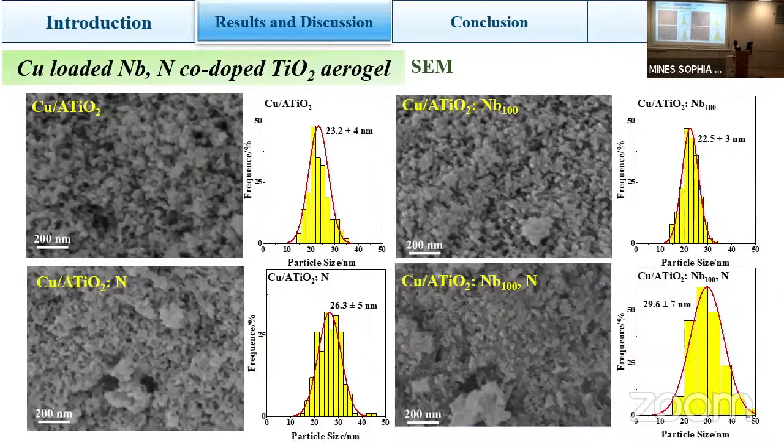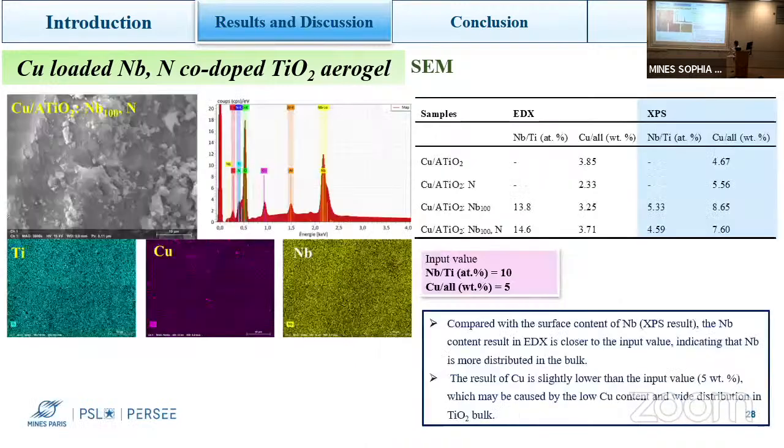And then we're using SEM to characterize its morphology. You can see that even loaded with copper, with metal, and calcined in ammonium, our catalyst's TiO2 particles still remain small. It's a smaller particle size. The maximum is around 30 nanometers, still a small particle size.